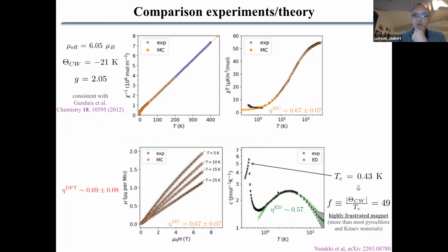It's classical. It's just that this part here and the specific heat going down cannot be described by continuous classical spins. You need to consider discretization to be able to see that, because continuous spins have an ill-defined entropy and specific heat at low temperature. So that's a problem of classical spins more than the material itself. But once you induce a bit of this discretization, that's what we have done there, you can recover this bump here.